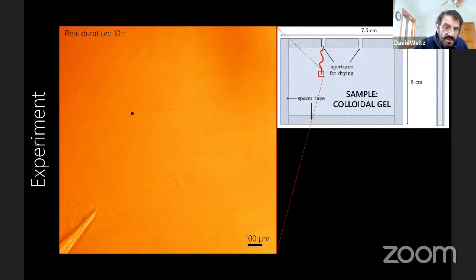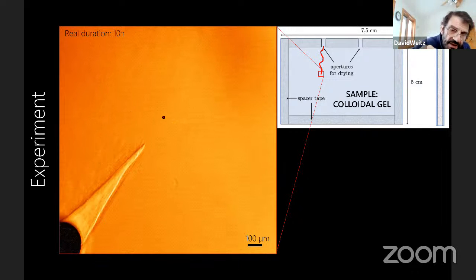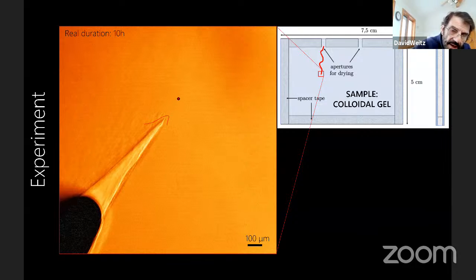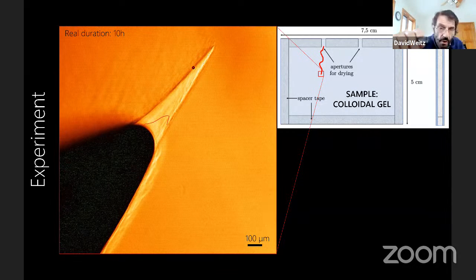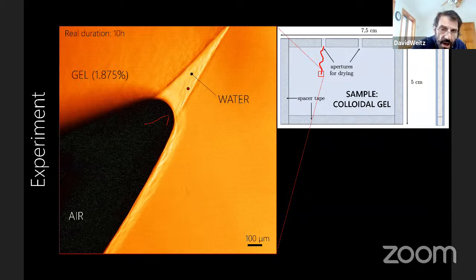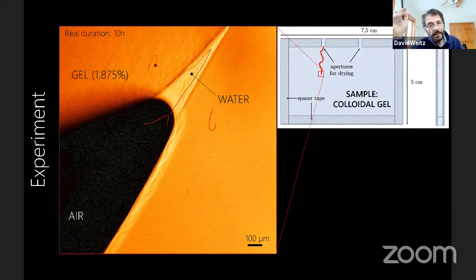And when you do that, you see here's the crack. And notice here's the crack moving in this direction. Here's the air. And notice that there's a whole layer here of water. Here's the gel. There's a layer of water that's pulling apart. So you're cracking the gel. And this, in a sense, is what you have to do, because this sample probably has a few percent colloids, a few percent gel. It's mainly water. So in some sense, you're cracking the water. You're pulling it apart. This is about 2% colloids. You're pulling it apart, but you always see this layer of water.